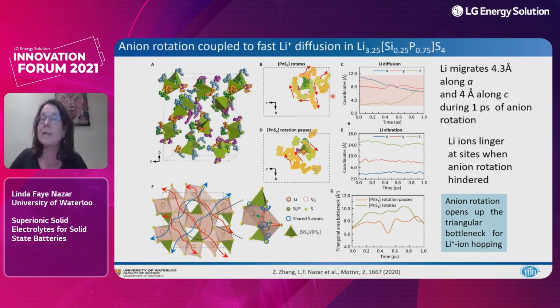So what's important is that if you look at the lithium diffusion in that same picosecond time frame, shown here, the lithium migrates 4.3 angstroms along the A-axis, and it migrates about 4 angstroms along the C-axis. And that is exactly the distance of the unit cell, basically from one lithium ion to another. So it basically moves 1 lattice hop during that picosecond rotation. And there are spots in the simulation in which the PS4 group does not rotate, and at those points, the lithium do not migrate. They just linger at their sites.